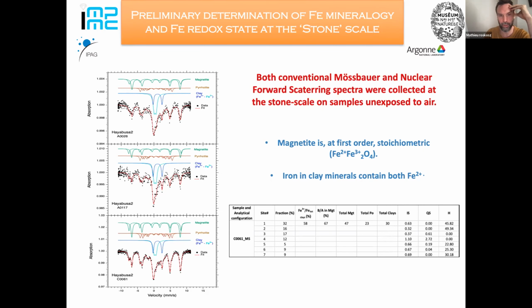So we were able to fit the spectrum with 7 lines. 5 of them are sextets corresponding to magnetite and pyrrhotite, and 2 of them are more typical of iron 2+ and iron 3+ in silicates, let's say, or oxides.